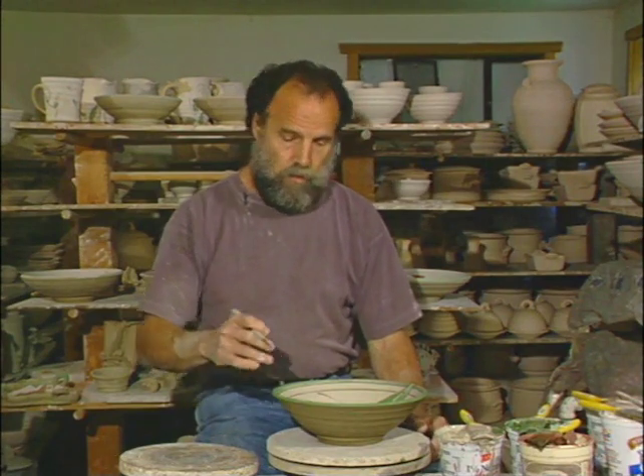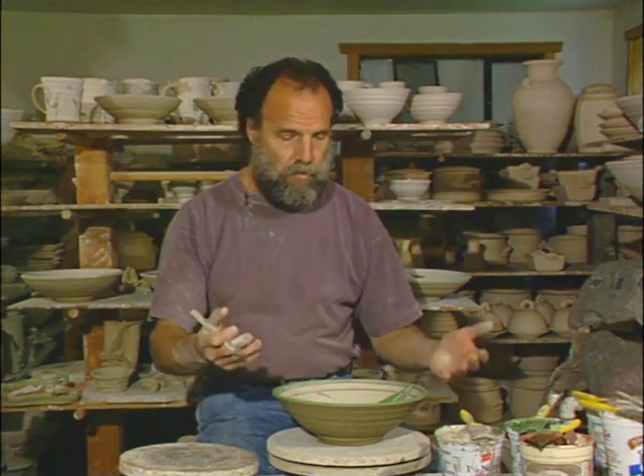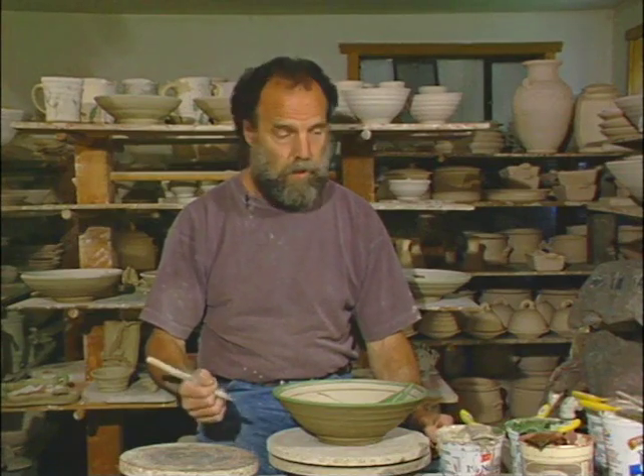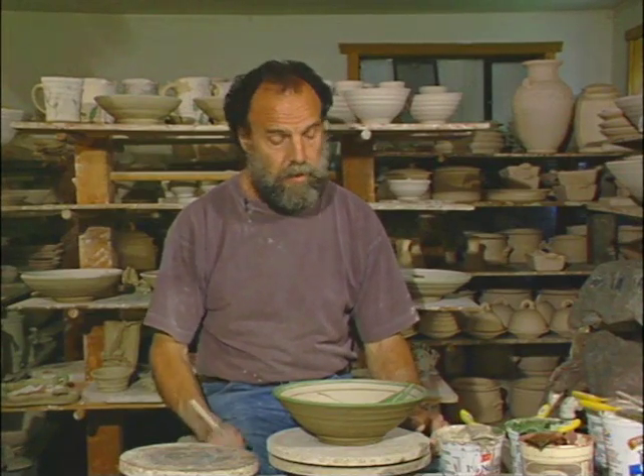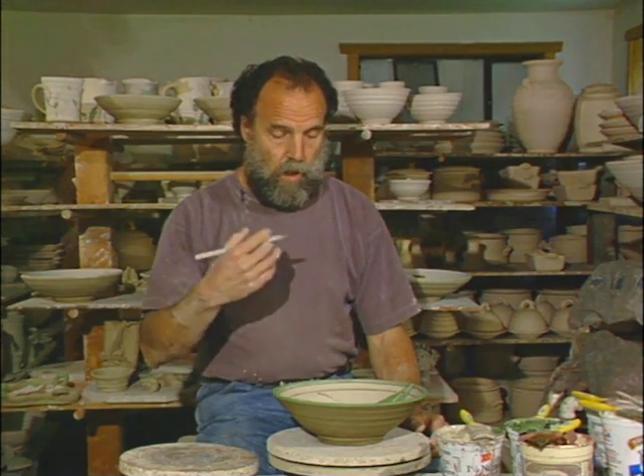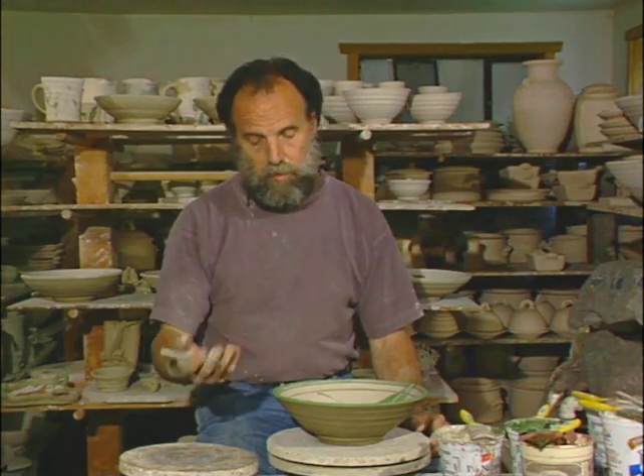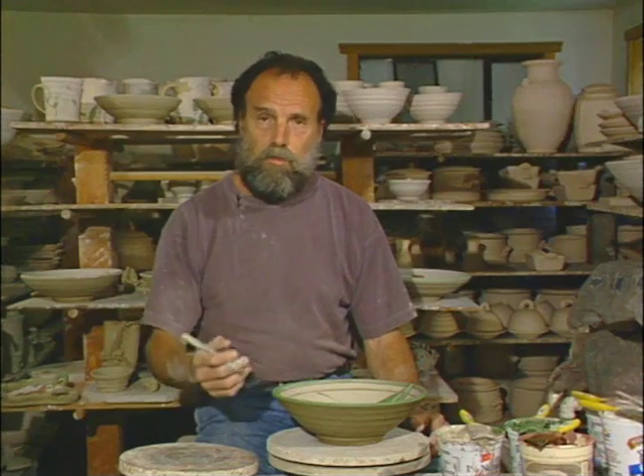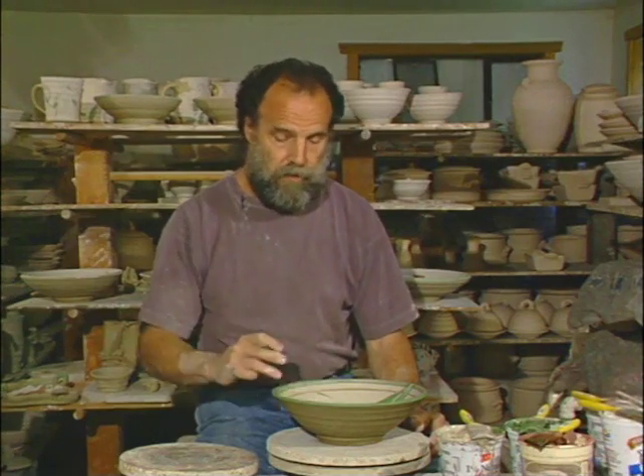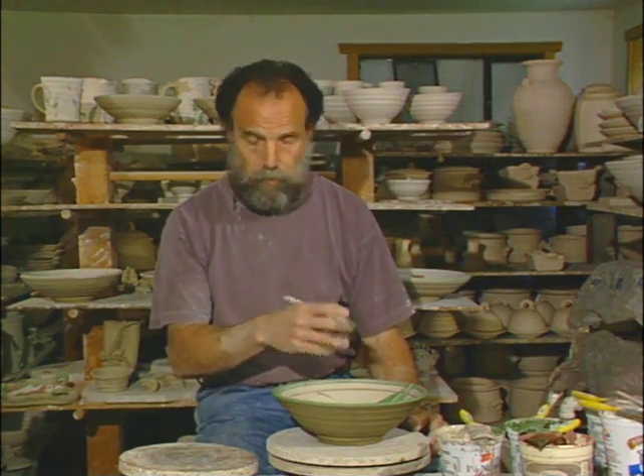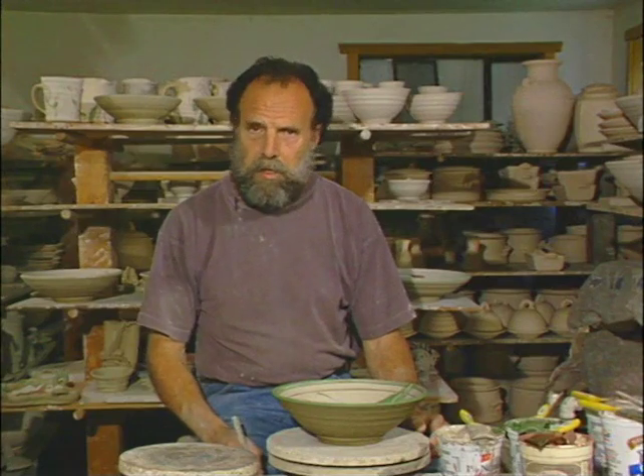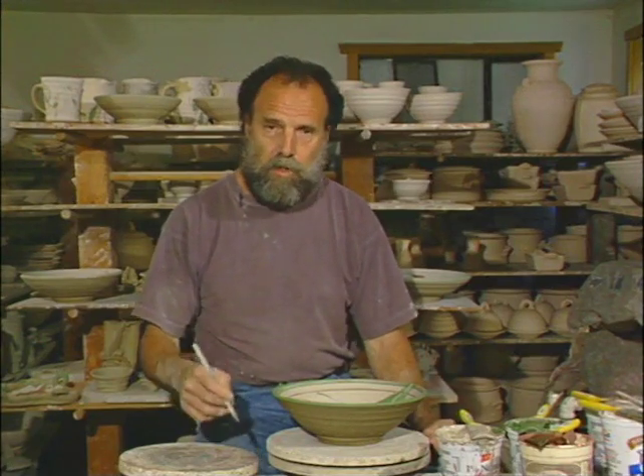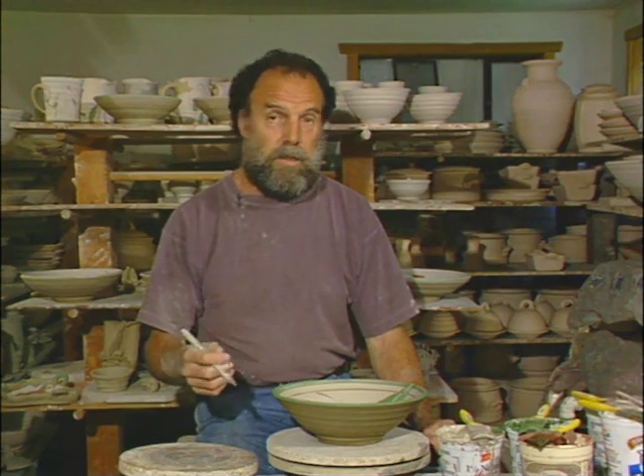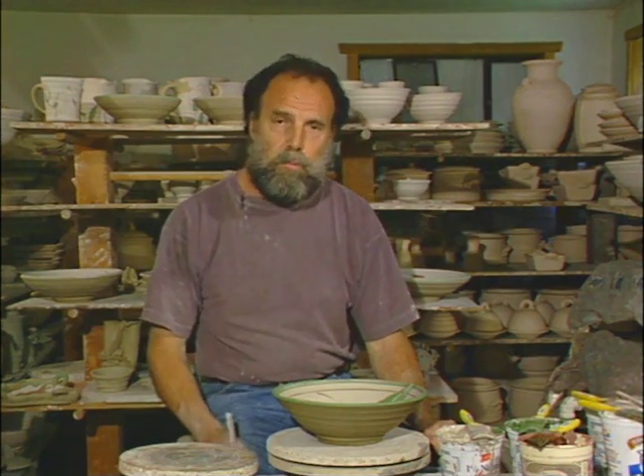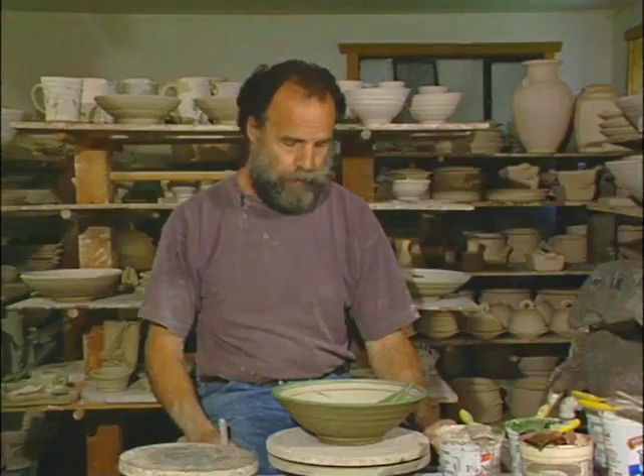As the pot dries, the slip will dry with the pot and stay adhered to the pot. That's the first essential element of a good slip. If you change temperature or have some particular requirement with the clay, you may have to do some experiments and adjust the fit of this slip to your own clay. We've done those experiments for you for this initial beginning point, and this slip should fit any normal terracotta. The ingredients for the slip, the recipe, is listed with the cover, and we'll show you later in the program how to go about mixing the slip up.